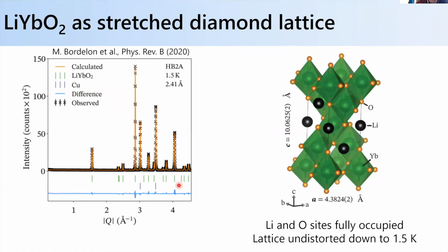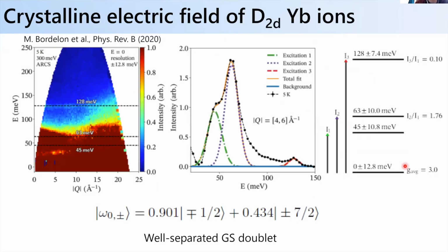And so, okay, so here's just the material, and this is sort of the obligatory neutron diffraction we've done. The lithium and oxygen sites are fully occupied from the neutron diffraction, and the lattice remains more or less this I41/amd, like we expect it to be, down to 2 Kelvin, okay? So we can do the same thing. We can look at the crystal field levels, and all this is showing you is that we can solve the crystal field Hamiltonian. And again, it's a well-separated doublet with the first excited state around 45 millivolts. The details here are not super important for the remainder of the points I want to make, but just to show you that it is indeed a J effective 1/2 regime.